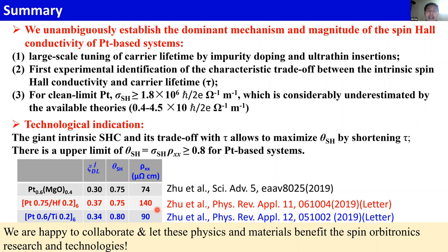Thank you. And you're probably aware that in the past couple of years, there are papers reporting the platinum spin diffusion length can actually be as large as 8 nanometers. Yeah, and that's from an inverse spin Hall experiment. That's right. So if that was true, how do we reconcile these two different results? If the spin diffusion length is really that long, does it mean that the spin-orbit torque may not come from the spin Hall effect?